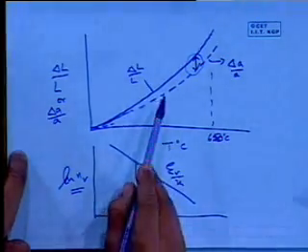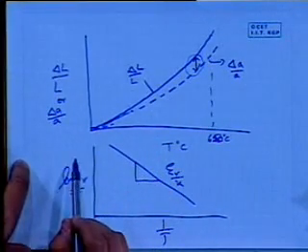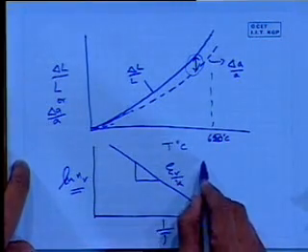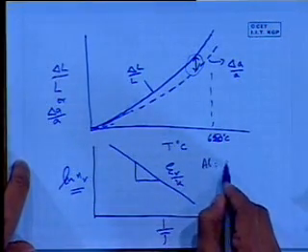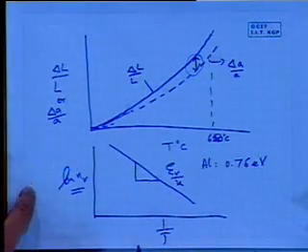So experimentally, I can determine vacancy concentrations at different temperatures, and then plot this to extract the answer. In the case of aluminum, it turns out to be something like 0.76 eV. So it requires about 0.76 eV per atom to create a vacancy in aluminum.